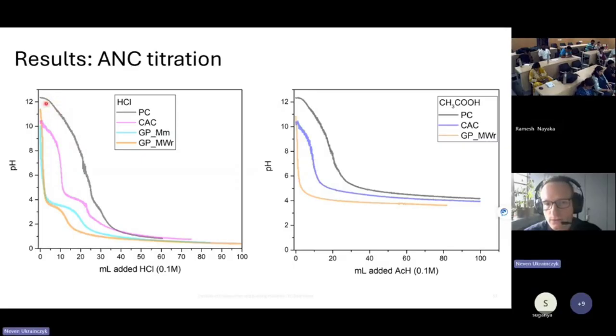So this is because of the dissolution of portlandite and CSH here, and then you have here alumina gel, probably in dissolution, and then there is no buffering at low pH. Now for alumina cement, it actually has lower buffering capacity than Portland cement, but it has a better buffering at lower pH. And this is why alumina cement performs good in sewer systems, because here you have this alumina gel formation, which maybe also works as antibacterial because of aluminates, and you have closing of the pores at pH of 4. But if you go below 4, then you are dissolving this alumina gel, and then again you have a very high dissolution.